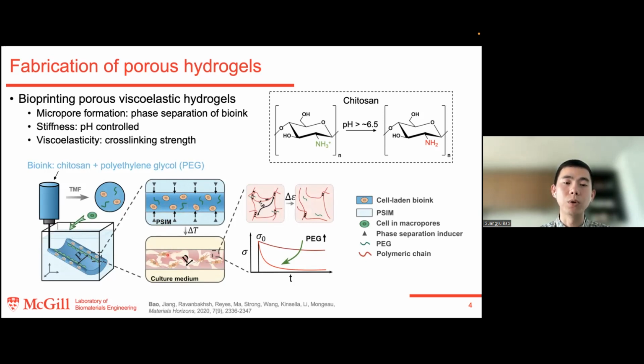This polymer-poor phase will become the interconnected pores, because it mainly comprises water. Inside the solid phase, the polymer-rich phase, the chitosan will be stabilized through hydrogen bonding between the chains themselves, and they will form the porous chitosan scaffold. By tuning the PEG concentration within the bioink, we can also tune the viscoelasticity. The PEG basically acts as a spacer among the crosslinks, which can tune the cross-linking strength, which corresponds to different viscoelastic responses.